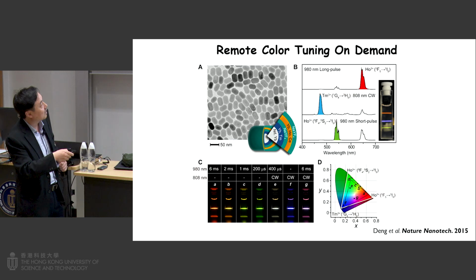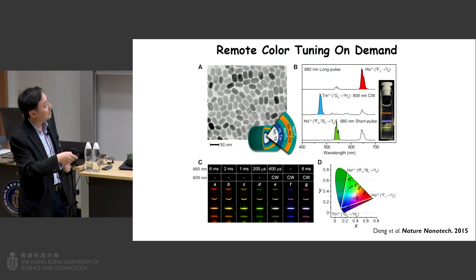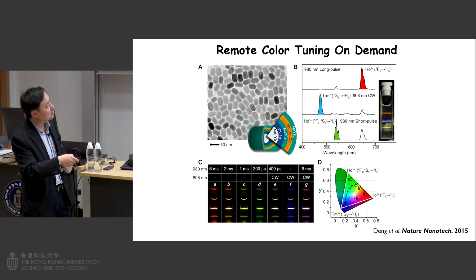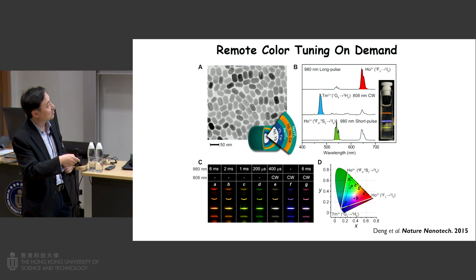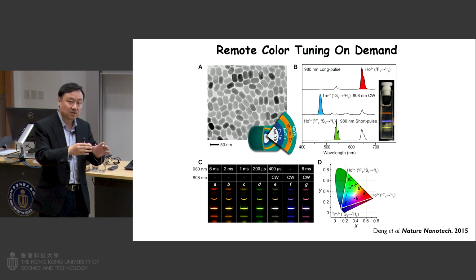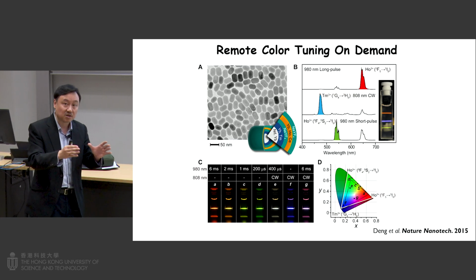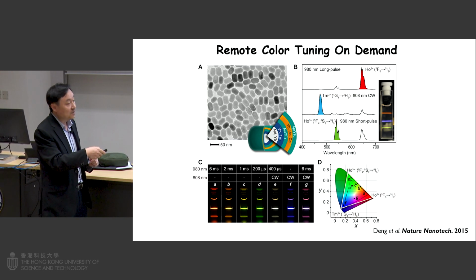Let's see the results. You can see here the particles dispersed in solution. Then we use 3 different laser sources. The top one is 980 nanometer long pulse. The bottom one is 980 nanometer short pulse. The middle one is an 808 nanometer CW laser. So you can see the laser source is different, the excitation condition is different, and they give us completely different colors.